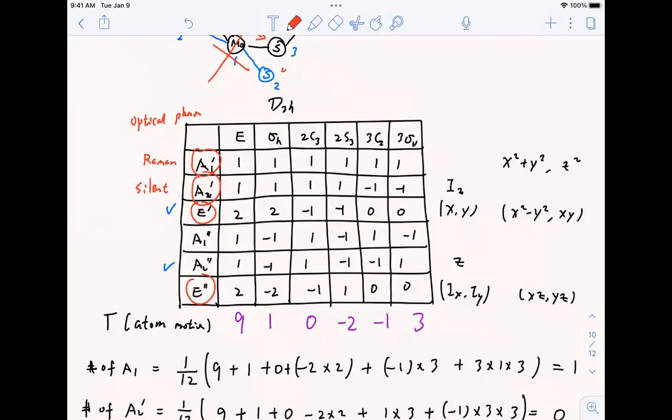Is it okay? So it doesn't mean you shine the light, measure the Raman, and you see everything. Some of the phonon modes are hidden. You determine this from the symmetry property, and that actually corresponds to a certain rotational mode. But for a lattice, they don't rotate, so you don't have this mode. You don't see this.